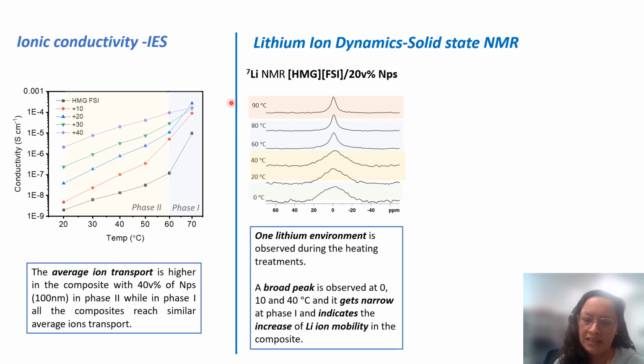We also studied the lithium-ion dynamics using solid-state NMR, and we performed static experiments in the composite with 20 volume% of nanoparticles. We found at lower temperatures a broad peak, which means that we have a lower ion mobility at these temperatures, but once we reach 60 degrees, the peak becomes narrow and it indicates an increase in ion mobility.